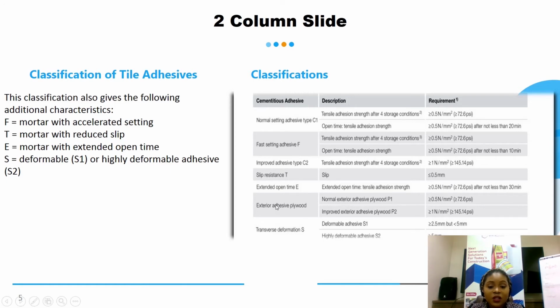Then for exterior adhesive plywood, you want to apply your plywood. You have the plywood P1 and P2, just as you have the C1 and C2. So you have greater than or equal to 0.5 Newton per millimeter square, and greater than or equal to 1 Newton per millimeter square. Then we have the transverse deformation S. So for deformable adhesive S1, we're looking at deformation of greater than or equal to 2.5 millimeter, but less than 5 mm that it can withstand. While highly deformable adhesive S2, we're looking at greater than or equal to 5 millimeter.